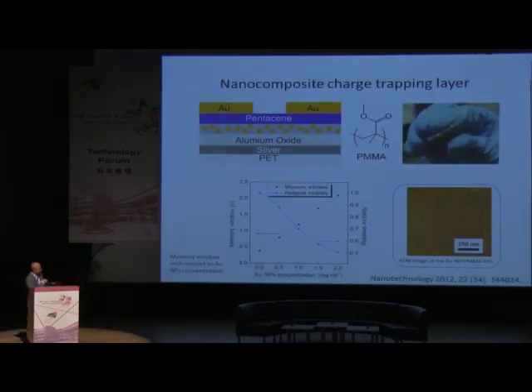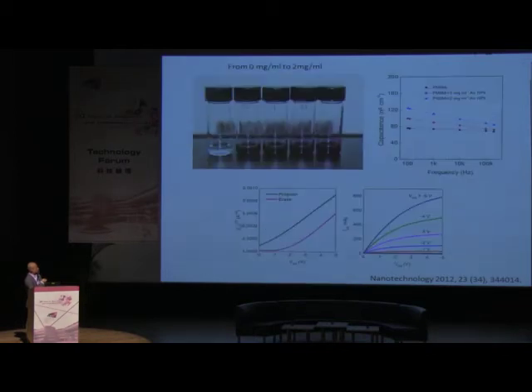And also we made one layer of nanocomposite, just embedding those nanoparticles, okay? It is a simple device, with only one layer of charge trapping layer, as well as an interface between the blocking layer and the semiconductor. It's a low voltage device because it's a polymer, and you can have a 1 volt memory window, but it's much smaller than the previous multi-stack devices.